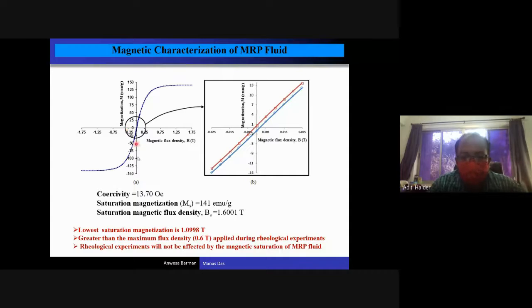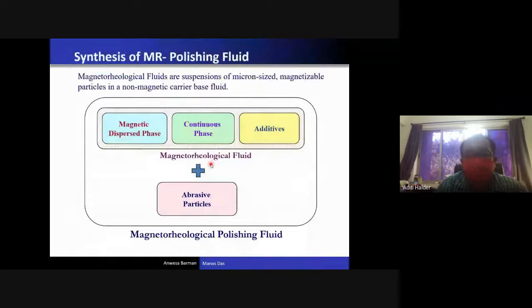Here, with this device, you can see an image, a curve of magnetization versus magnetic field. You can see this in the hysteresis loop. You can see the remnant magnetization here, and this remnant magnetization is very, very less. In the case of this MR fluid, you have to keep around 2 to 5 ml of this MR fluid inside a small plastic chamber, and then magnetize it. And then you can see the remnant magnetization is less. So when remnant magnetization is less, if you demagnetize, then immediately these iron particles also demagnetize. So less magnetization will be there, and agglomeration can be avoided.